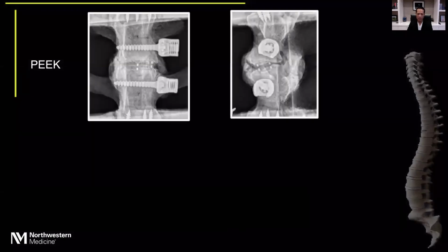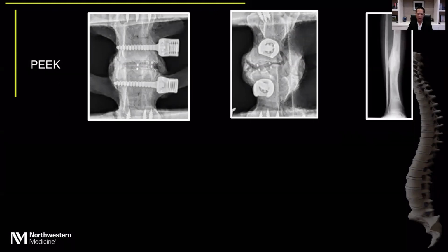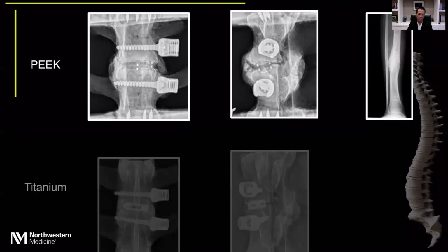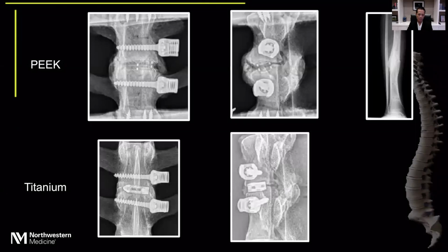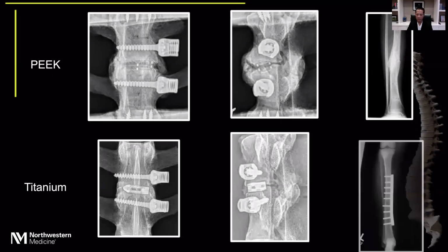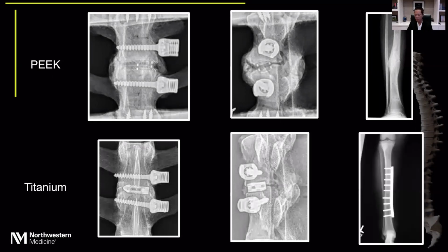This is consistent with what we see in an in vivo setting as well, where PEEK cages lead to inherent micromotion that then leads to a hypertrophic type of callus that we see with fusion, whereas titanium can often provide, with the friction, immediate stability. We see more of a uniform healing, much similar to that of an ORIF of a fracture from bone.